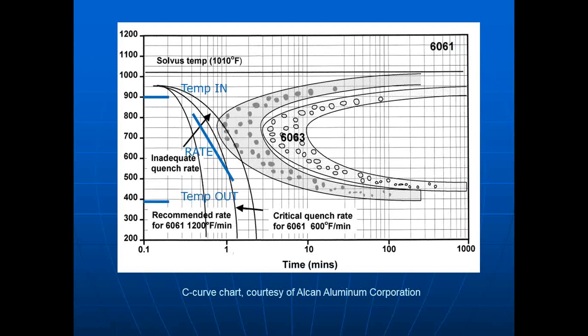We then see the rate. We need to reduce the temperature rapidly enough that we don't fall into the C-curve, the shaded area. And then we have a minimum temperature, the temperature out, which needs to be below 400 Fahrenheit.